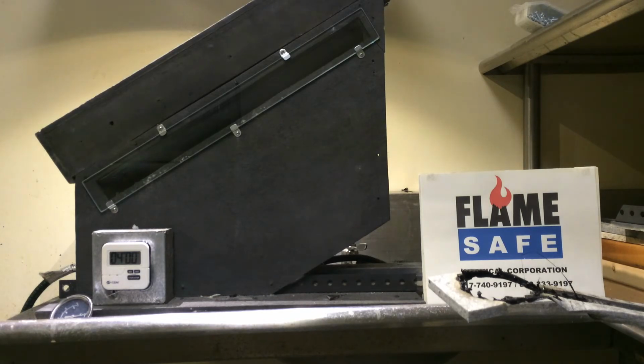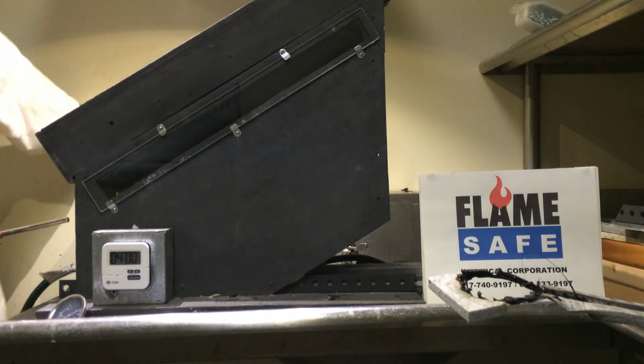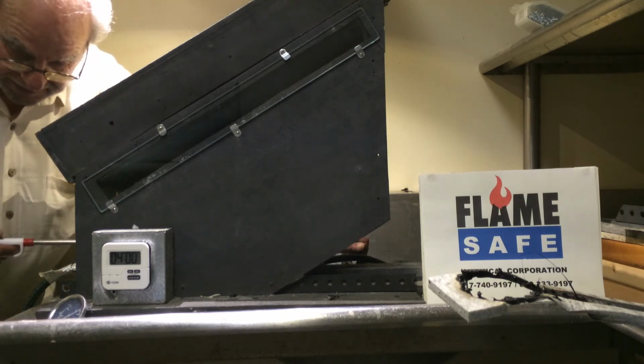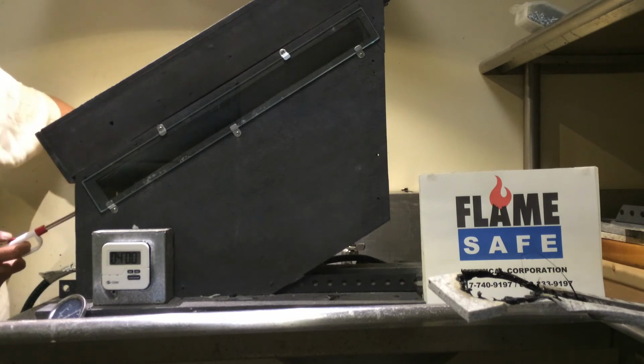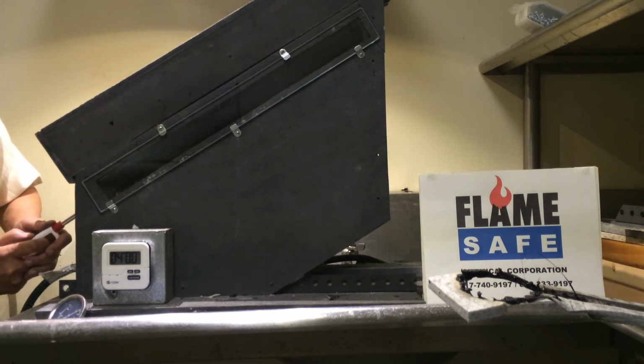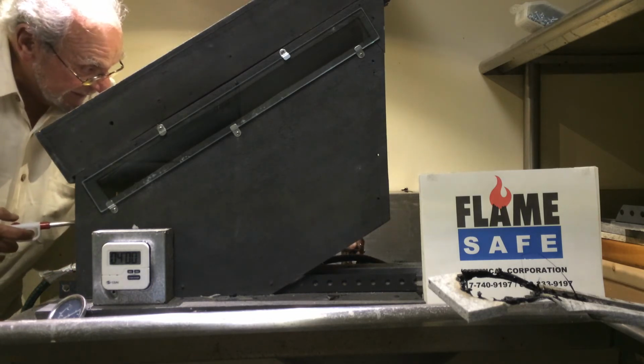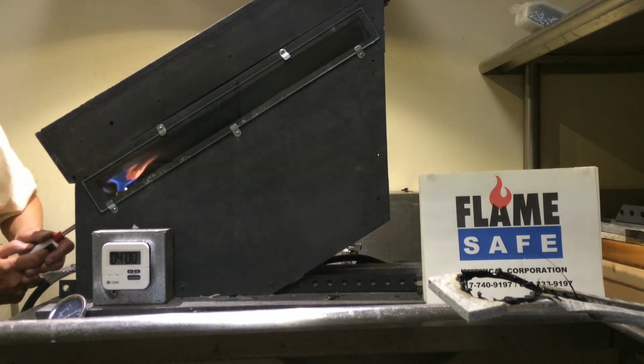This test method provides a relative flame spread of an experimental coating using small scale specimens. By calibrating this 2-foot test method to test method ASTM E84, you'll get the relative flame spread rating of the product. The intumescence was so great on this specimen that it expanded to such an extent that it put out the Bunsen burner.